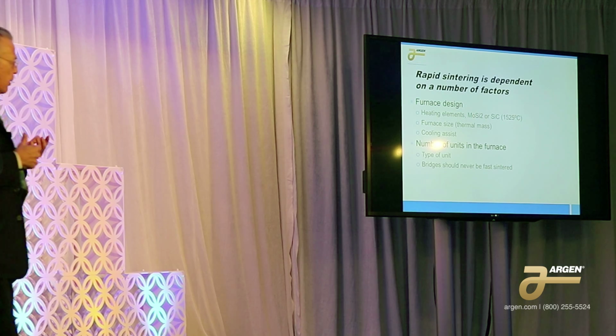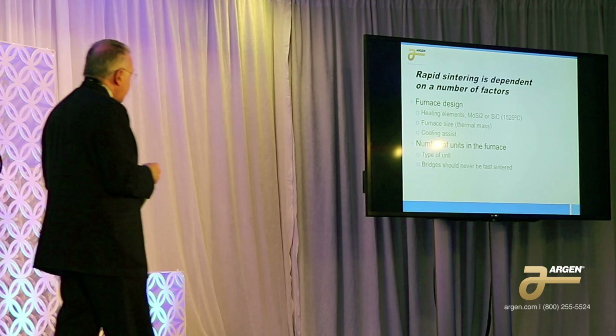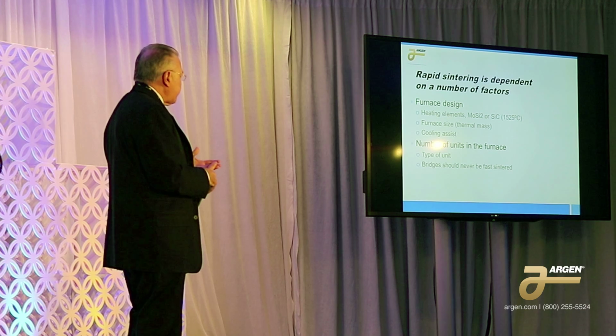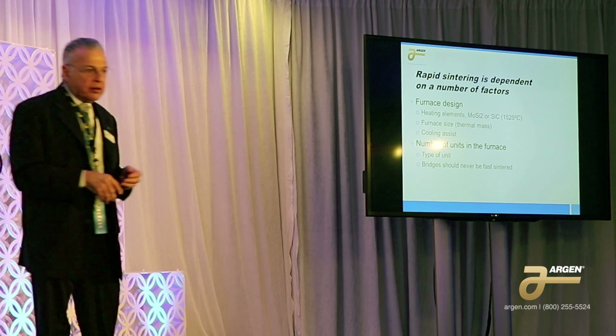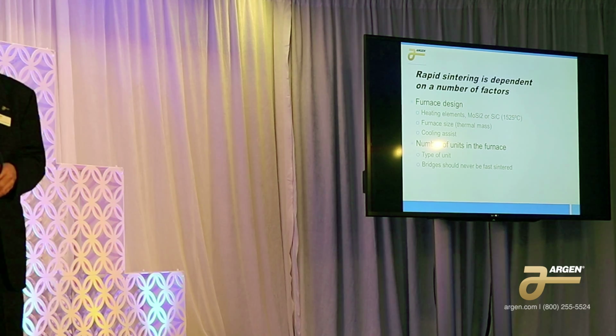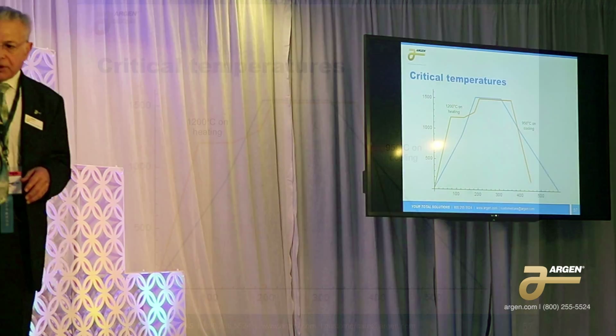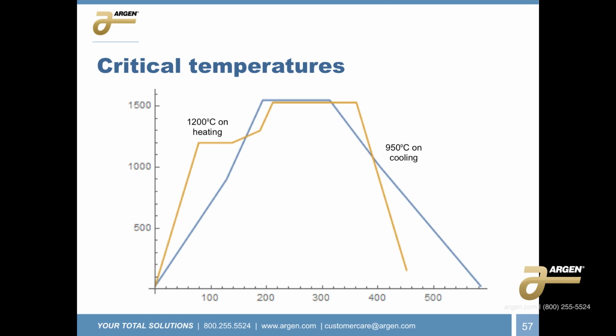As I said, the rapid sintering is depending on the furnace design and the number of units in the furnace, not on the material. As long as the material can fit into that 1525 or 1530 sintering temperatures. Now, there are 2 critical temperatures for zirconia. One on heating is 1200 degrees, and one on cooling is 950 degrees.